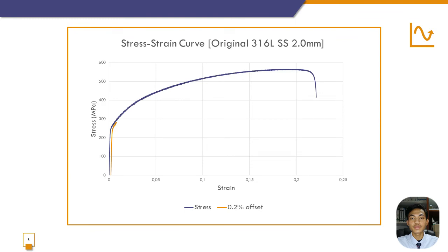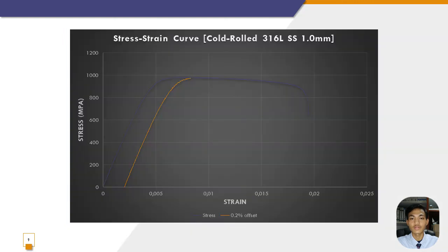To know the difference between these two specimens, two tensile tests have been performed on the original and cold rolled specimens. As you can see, the figure shows the graph of the stress over strain curve of the original stainless steel 2.0 mm, which was tested until the maximum applied load of 10.38 kN before the specimen fractured. For the next figure, the graph of the stress over strain curve of the cold rolled stainless steel 1.0 mm was tested until the maximum applied load of 8.02 kN before it fractured.